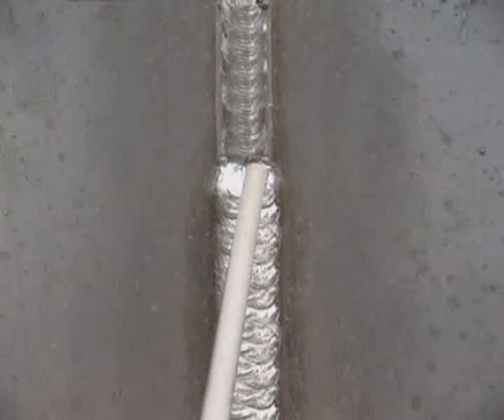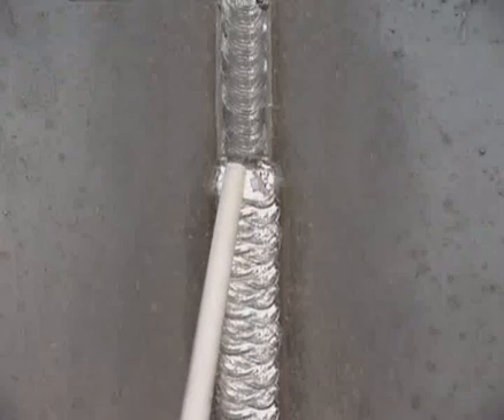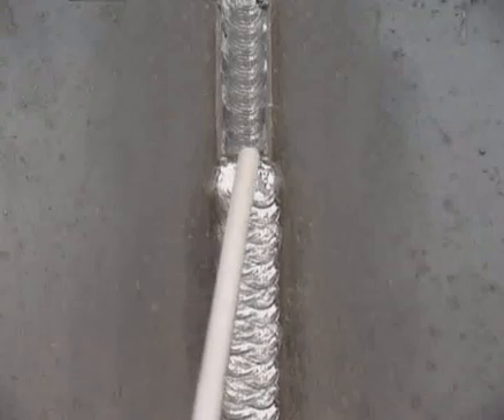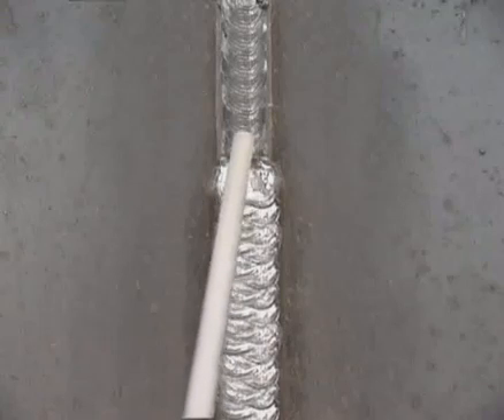Start on one side, letting the puddle flow out to cover the edge of the bevel. Cross the center relatively quick to the other side and hesitate until the puddle flows out and covers the edge. Move the rod up a little, then cross, hesitate, move up, and cross. The upward progress is going to be slow, heating the base metal up more, so turn the amperage down a little. Use the edge of the bevel as a guide to keep the sides of the weld straight.